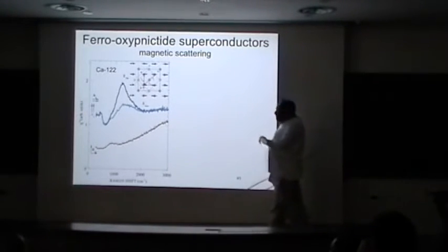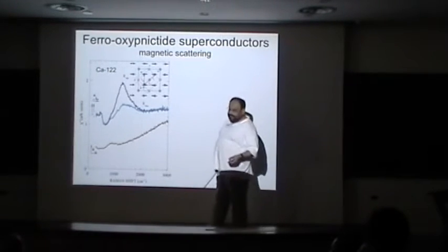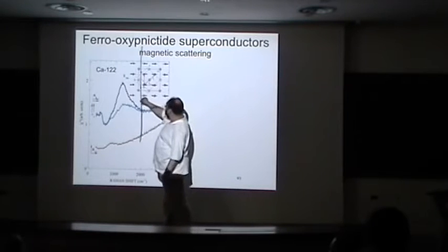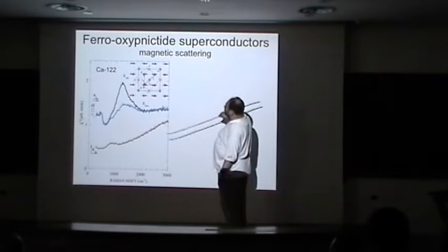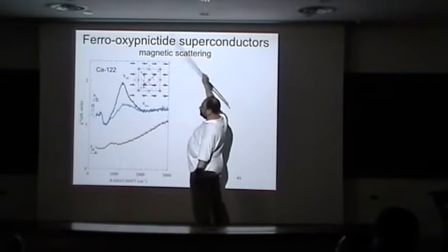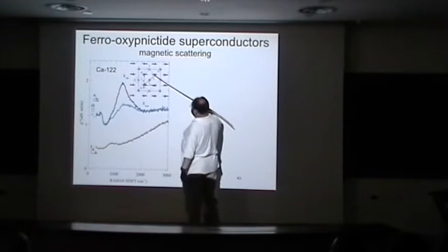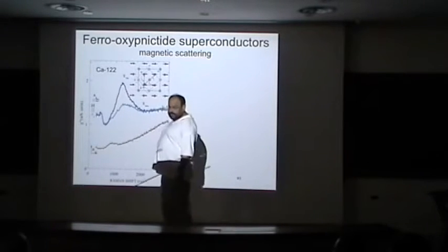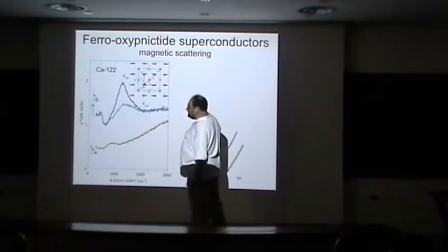Now, I just want to mention other things that can be done with Raman scattering. We can do magnetic Raman scattering. In this case, if we have an antiferromagnetically ordered system, we can come in with a photon, kick out an electron into an excited state, move it around without paying the Coulomb U, and let the spin from the ground state propagate, take the place of that hole and collapse that spin from above into the new position. That's a high probability exchange.